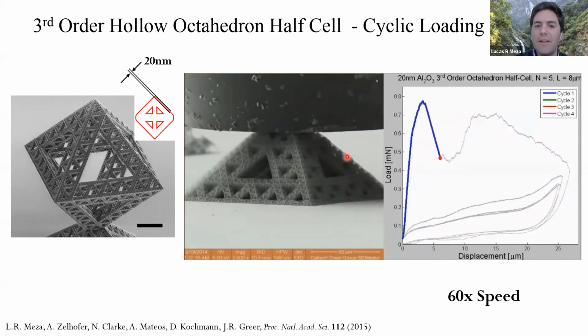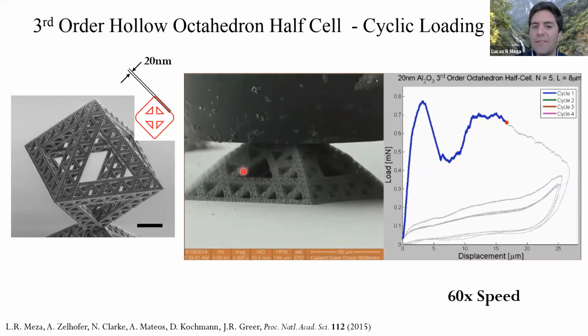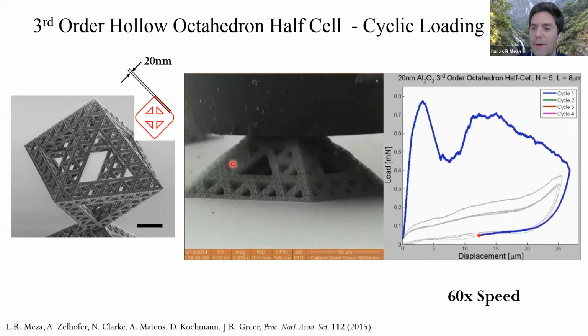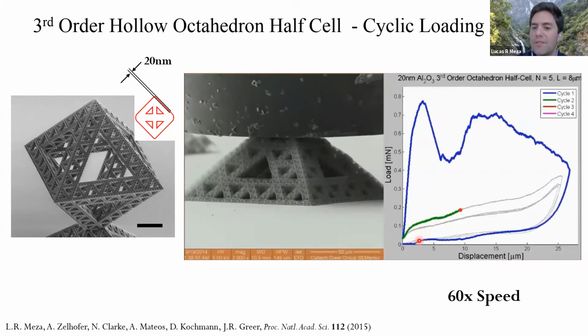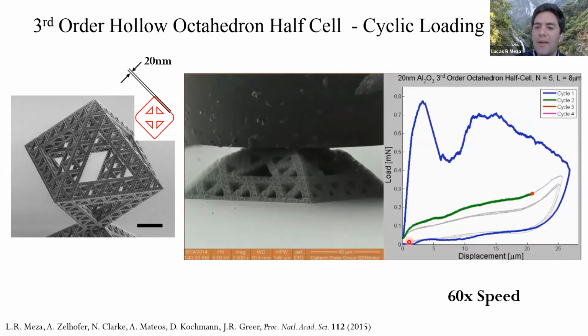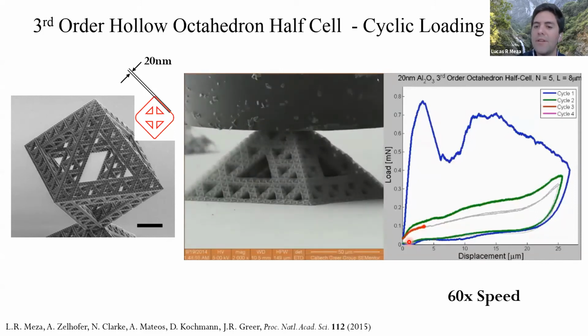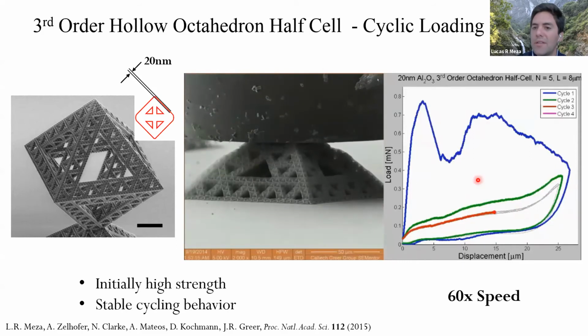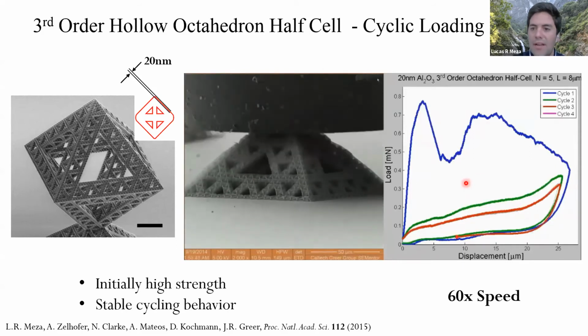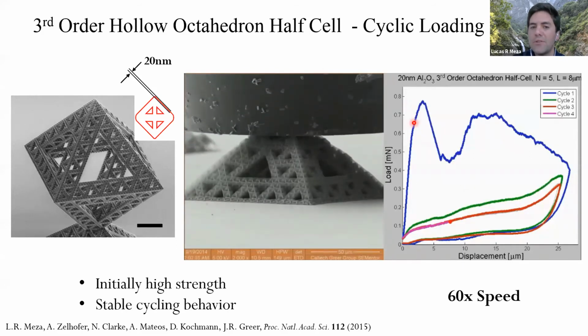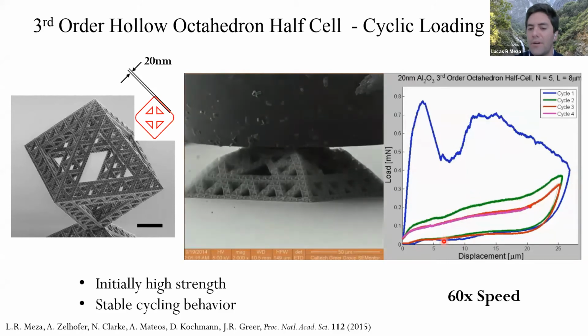Cracked parts of the beam stay cracked, and you have buckled pathways that form which reduce this initial peak load. But then you get to a pretty stable load cycle after just one or two cycles. So even though you lose a lot of that initial integrity, you're able to recover a bit better.